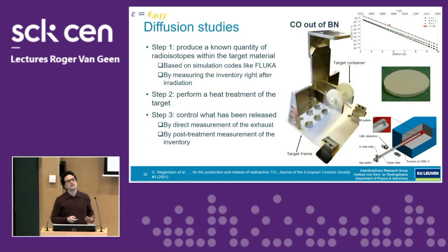Then there are diffusion studies you can perform. So here, that's a setup that was designed by Simon, one of my PhD students, where he put the target material in here, and this is the same structure as the ISOLDE target so that it could be brought at the ionization point. And then he opened that, he had put some pellets like this inside. He then used a setup in which he first measured the activity he had in his sample from whatever had been produced. You can also work with FLUKA simulation if you don't have this opportunity. Then he inserted this long tube into an oven from which he could very easily control the temperature.